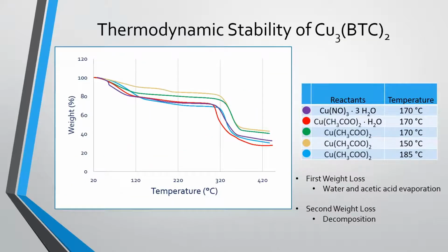Then we observed our thermodynamic stability. Our first drop can be seen here, which measures the weight percent change over a time period and temperature. Our temperature range was from 20 degrees to 430 degrees. Our first temperature drop was seen between 100 and 120 degrees, which is likely due to water and acetic acid evaporating. Our second, which is what we're looking for,